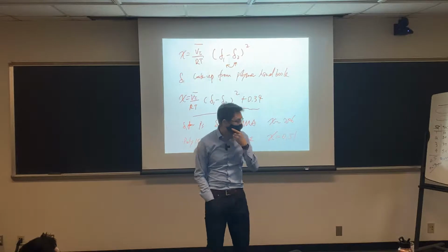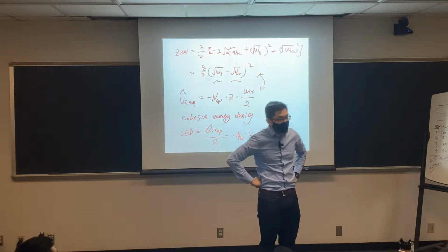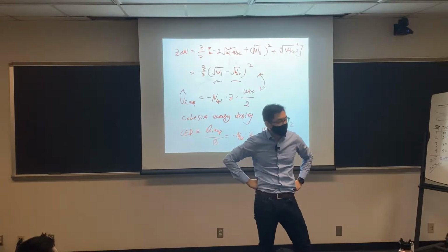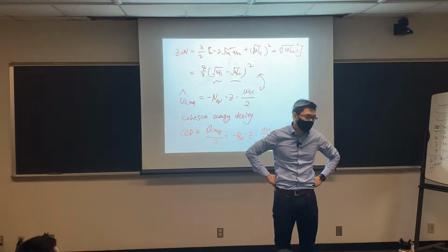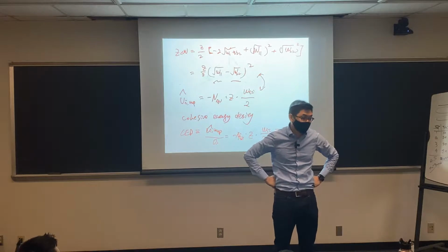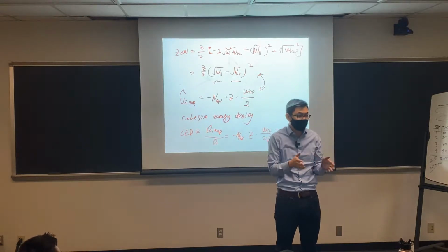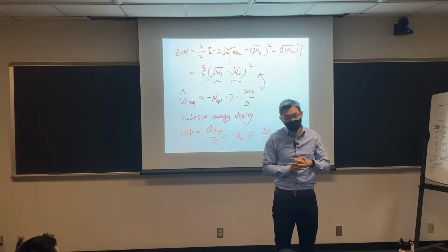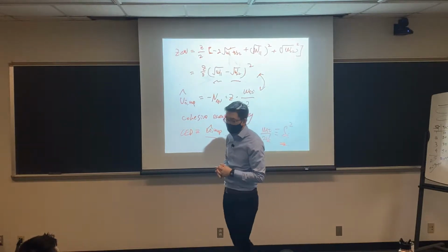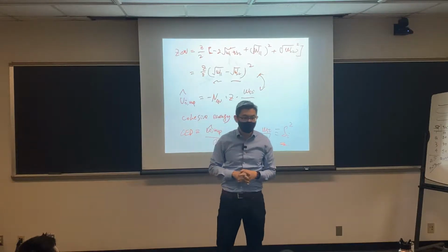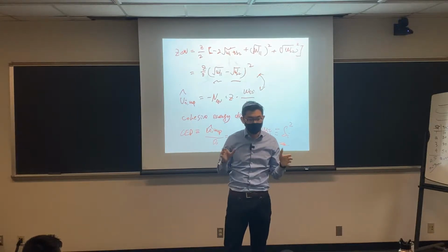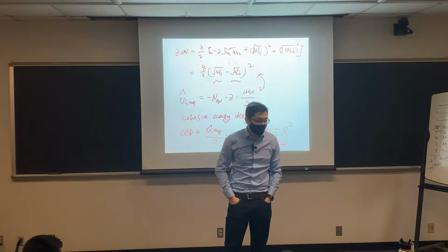So in other words, it's an entangled system, right? So it's not necessarily phase separating on a small scale quickly. You can see by optical microscope, which typically can look at features up to microns, but not at the nanometer phase separation. So X-ray or neutron scattering are very powerful. In the early days, you can look at how much scattering signal, which is proportional to phase separation, to look at those phase diagrams. Once you get the phase diagram, you can correct what the chi value is.